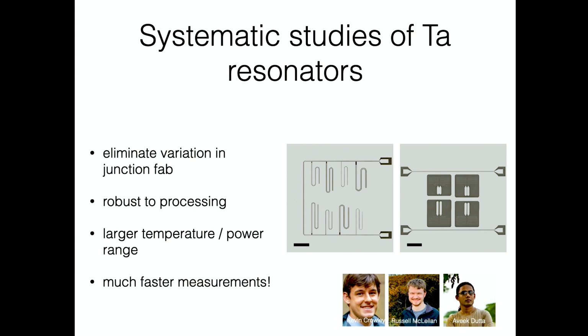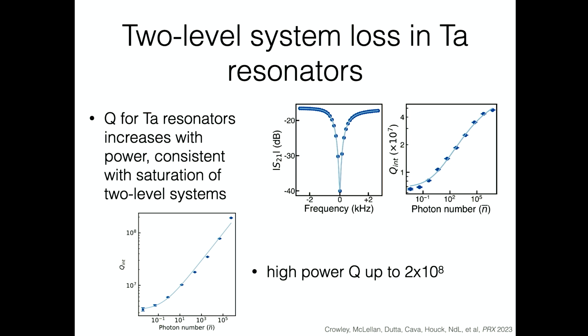And the idea is that we really simplify the measurement. So instead of just making a qubit where we have all of these different materials at play, we just have sort of one metal and one dielectric. And we can interrogate this over a very large range of parameter space to now try to use physics modeling to understand where our losses are coming from. So if I just look at transmission through these resonators, what I'll see is a little dip that comes from the resonance frequency. And then sort of, as a lot of people have seen, as we turn up the microwave power, the quality factors go up. So we see this behavior that's consistent with these saturable 2-level systems.